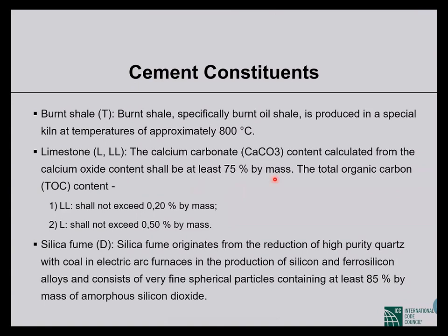So in case of this, there are some specific compositions: calcium carbonate should be at least 75% in the limestone. And organic carbon should not exceed these amounts for the different types, for LL type and L type.